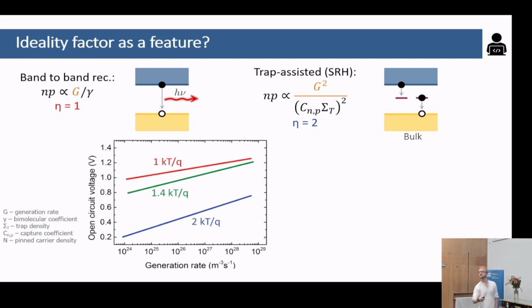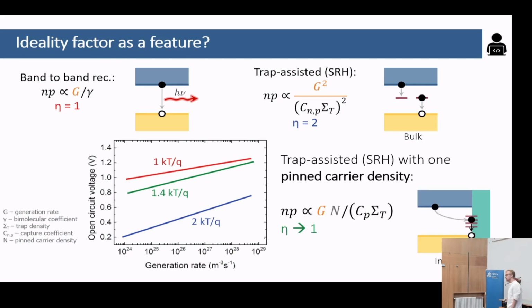Now, for anyone that works on perovskite, you know that most of the time when you make those measurements, your value is closer to something like 1.4, somewhere in the middle. And that very often comes from the fact that you're actually pinning one of the carrier densities. And if one is pinned because of many different reasons, for example, you have a strongly doped transport layer, or some doping in the perovskite that sometimes happens, or you have a very thin transport layer and the density there is pinned because of the electrode density, then you actually reduce that ideality factor. So using the ideality factor straight out of the gate is actually not so useful in perovskite because of that phenomenon. So you don't know if you have a mix of trap and band-to-band, or if it's a pinned carrier density and so on. That's why you need to go a bit beyond that.